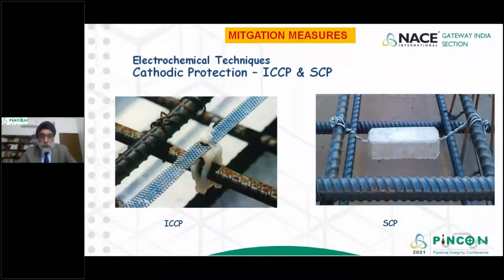Now, a commonly used system is using cathodic protection. As all of you know, we have either impressed current cathodic protection or we have sacrificial cathodic protection. Both technologies are used for preventing corrosion on the rebars. In an impressed current cathodic protection, we can use anodes which are embedded in the concrete, or we can use anodes external, that means it is kept in the soil, for structures which are below ground. ICCP is a very common technology. Obviously, when the structures are above ground, the only option available is to put the anode within the concrete. You can't put it outside because there is no means for the current to get delivered in an atmospheric condition.